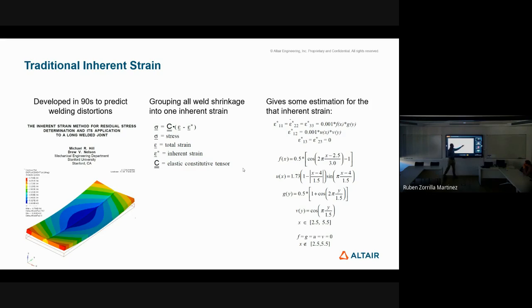In welding, they have formulations to calculate this induced strain, which they call inherent strain. And that inherent strain, they put inside the equation of state of your solid. Then they usually do linear elastic or sometimes elastoplastic. In fact, in welding, they do an elastoplastic solution, and with that they calculate a deformation, which is a good estimation of the total deformation. What's happening? They are not using temperature here, so it's not thermal at all.